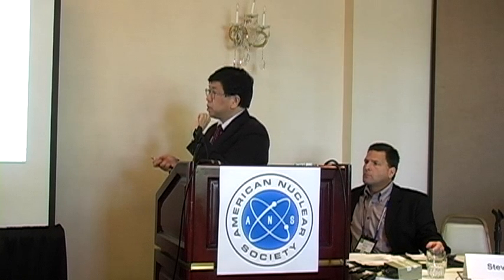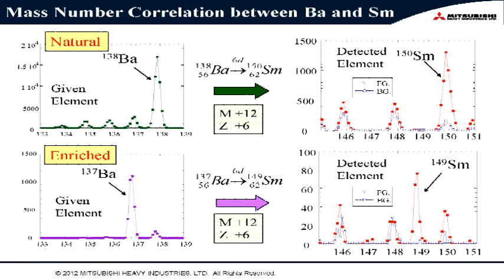The blue one is the background. Background means a sample with barium, but not permeated. The red one is the sample after permeation. We can see a significant increase of mass number 150 in this case. But if we put barium-137 on the surface, and after permeation, we get an increase of mass number 149. So these two experiments follow the same rule: the atomic number increased by 6 and the mass number increased by 12. And also in this case, the same rules exist for barium and samarium experiments.